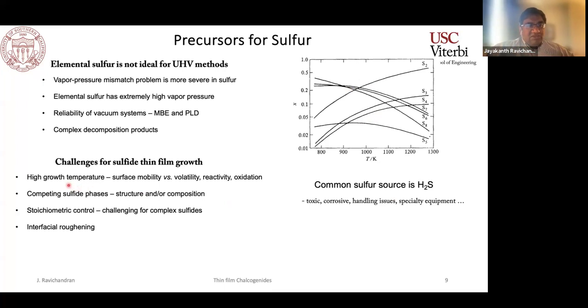So this leads to this very important challenge. When you have mismatched vapor pressure, you invariably have to grow these materials at high temperature, which is not favorable for your chalcogen, but at the same time your transition metal or other refractory species that are present in your compound would require higher temperature for increased surface mobility. This also leads to some uncontrolled reactivity issues of these species interacting with your substrate or within the material itself. Do they form uncontrolled structure or composition as you keep growing these materials? This leads to poor structural and compositional quality, and also interfacial roughening and intermixing and so on and so forth.